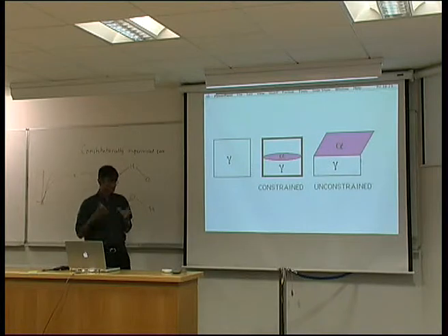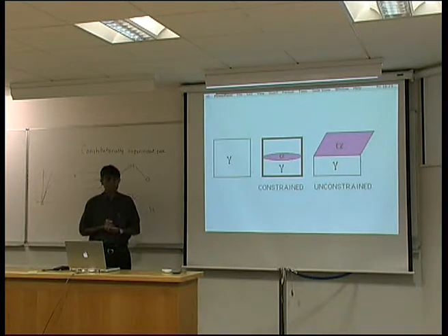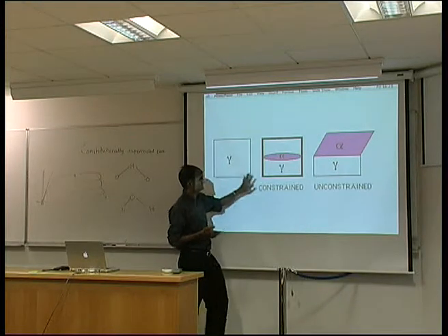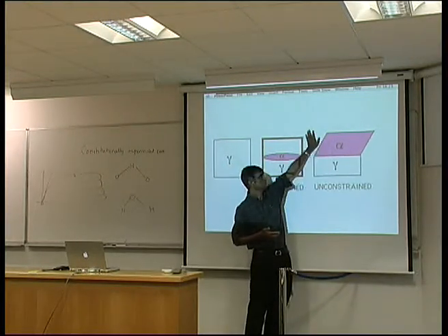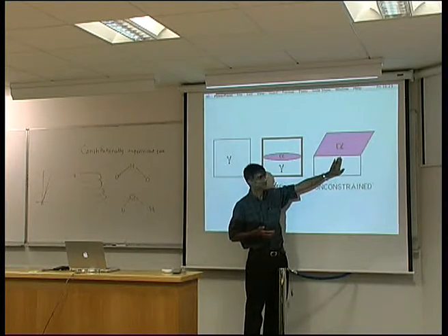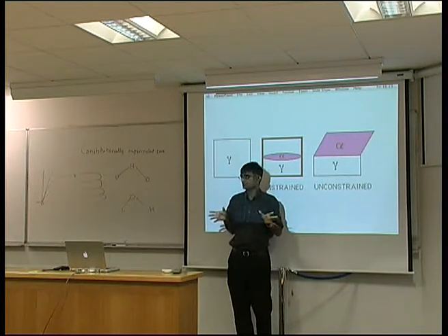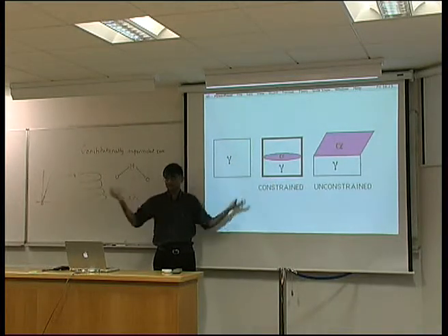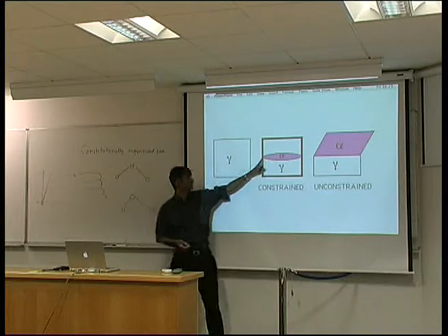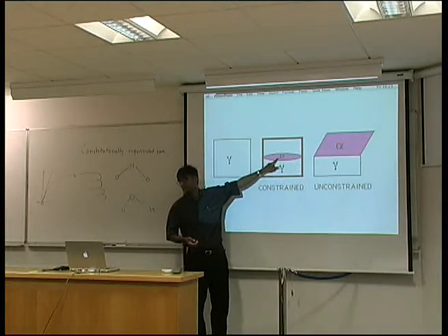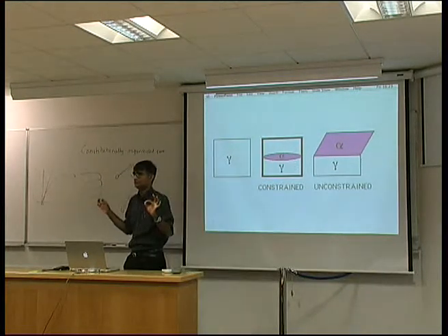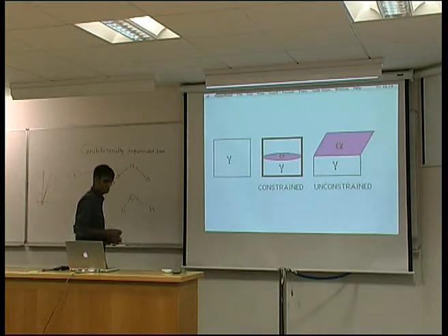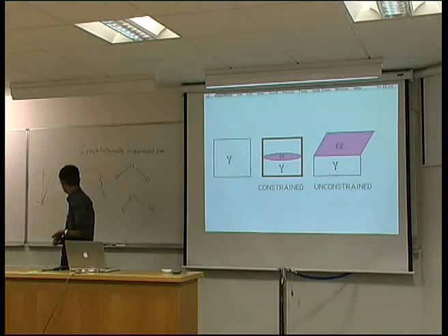So the essence of a displacive transformation is the strain energy. If I transform this crystal by displacive transformation with only air surrounding this, then this will be the shape and the strain energy will be zero. But if it is a constrained transformation, that means I have solid material around here, then it will form as a very thin plate, because a thin plate minimizes the strain energy. Now why is that the case? Why does a thin plate minimize the strain energy?